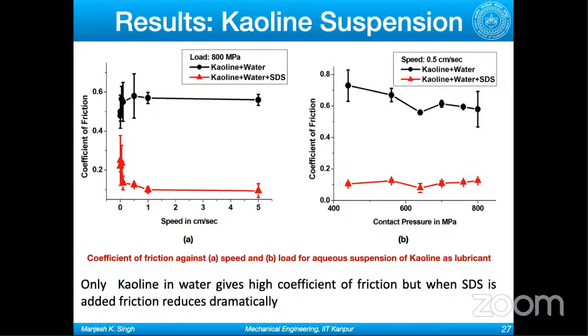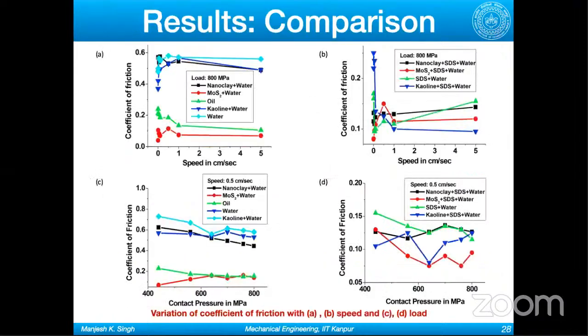But in case of MoS2, we got low friction without the surfactant. So with this, I'll just compare the results. What we can see, if you compare all the cases, is that MoS2 plus water without any surfactant gives us low friction, even lower than water, even lower than oil. So it is a good candidate. The other two candidates, nanoclay and kaolin, didn't perform as well or as expected.